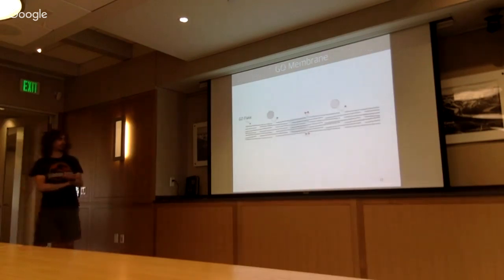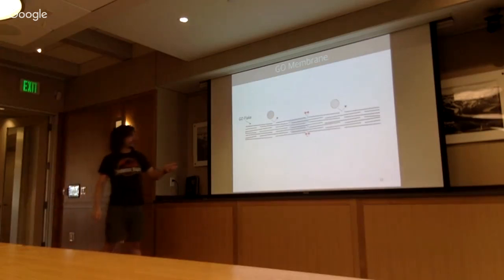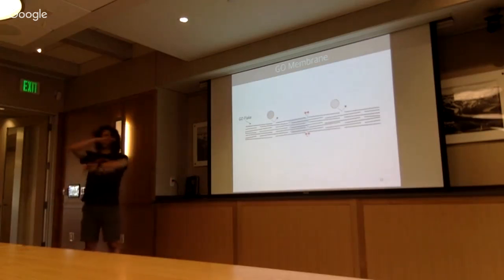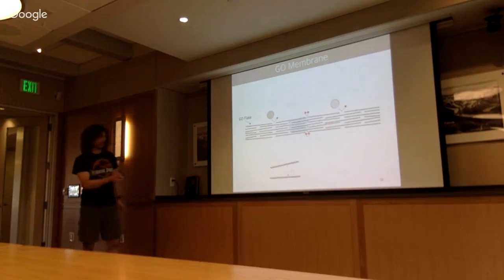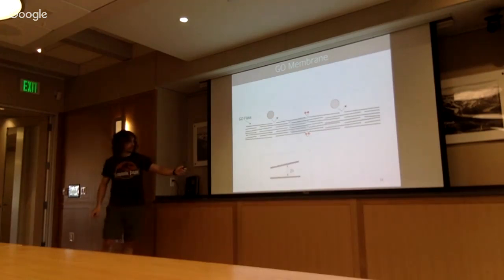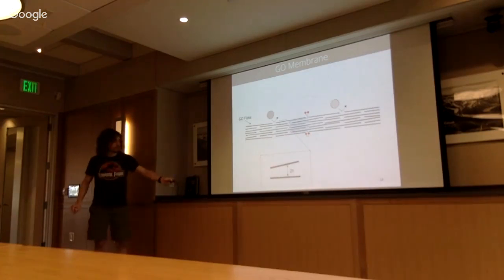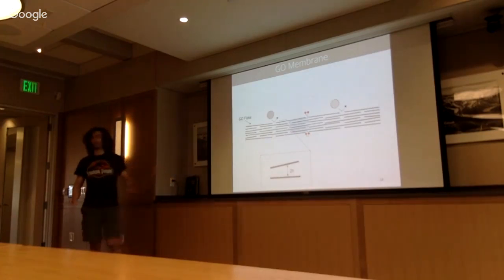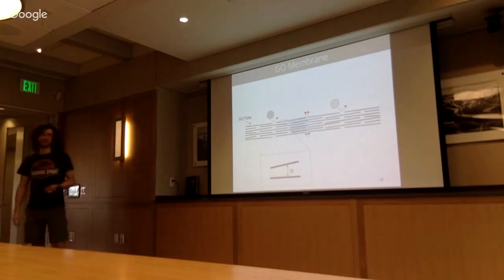How does it work? So basically, you can take just a graphene oxide flake, and then you stack flakes on top of each other, and then you're creating a sort of nanochannel here. And water is small enough that it can go through this nanochannel, but larger molecules, just by physical exclusion, cannot go through it. Thus, you create a porous membrane.